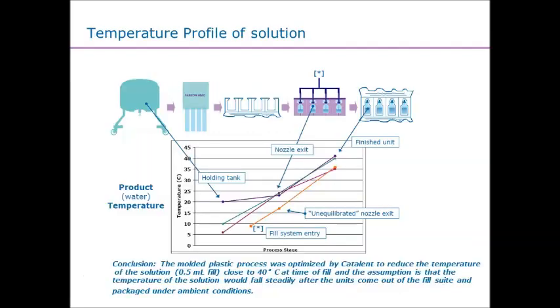There's been a lot of really good work. Even though you have 180°C of temperature coming out in the parison, that temperature dissipates very, very quickly. In a matter of about one to two seconds within contact with the mold itself, you actually get very good heat transfer and heat loss. There's been a lot of really good work done by the equipment manufacturers analyzing this. We've shown a peak temperature from the material coming through at around 40°C.